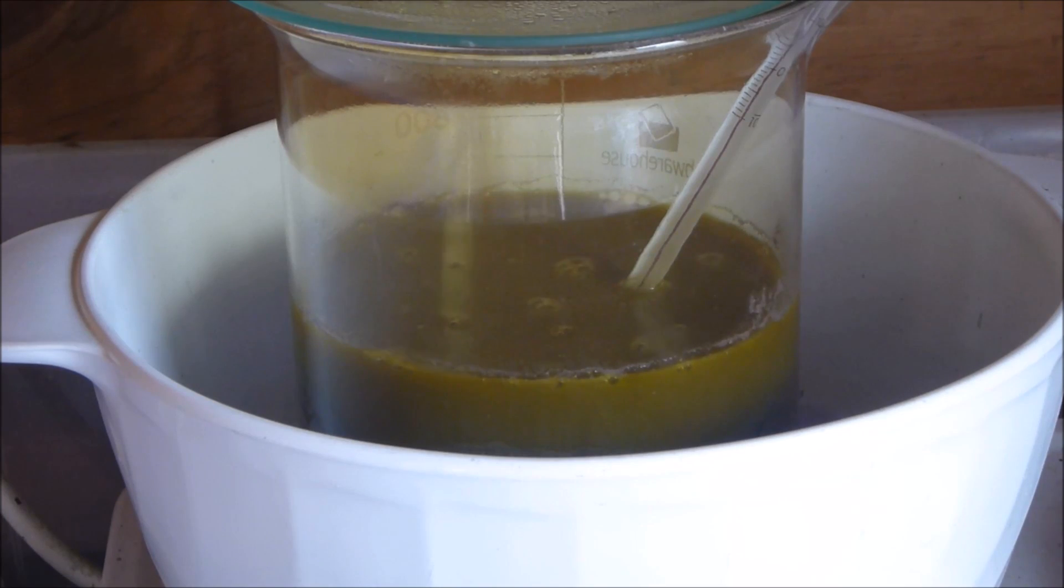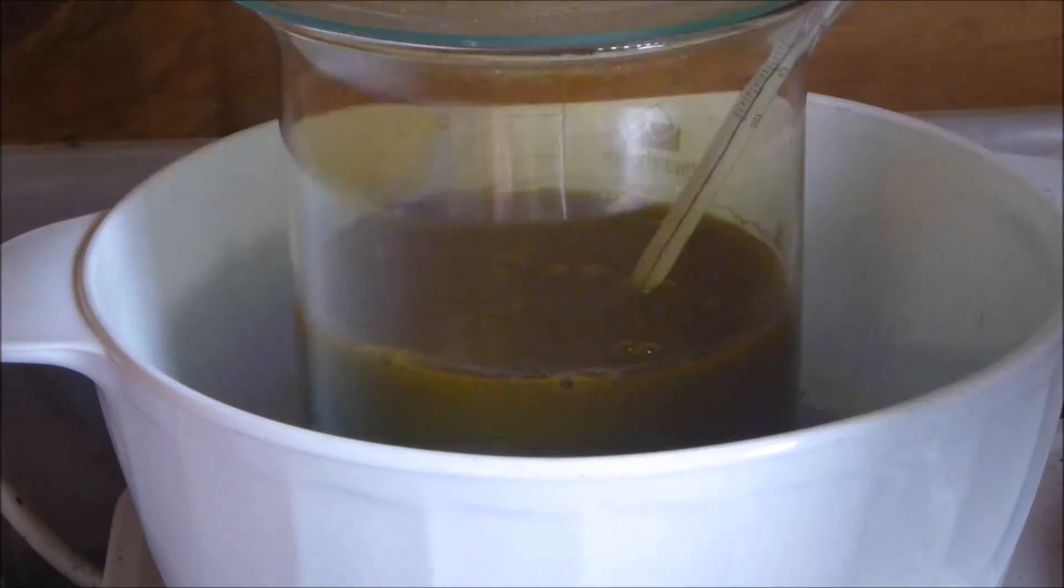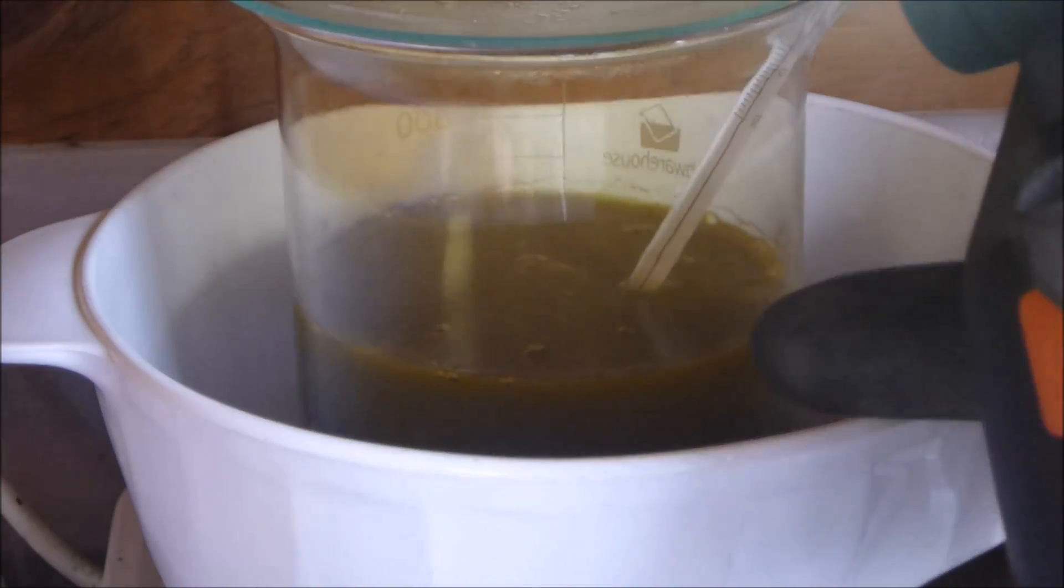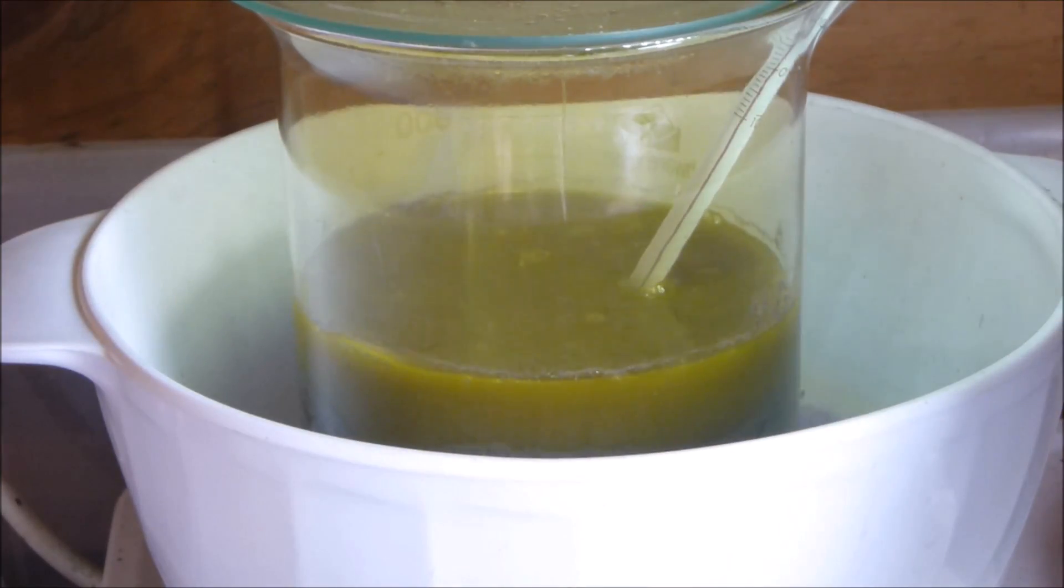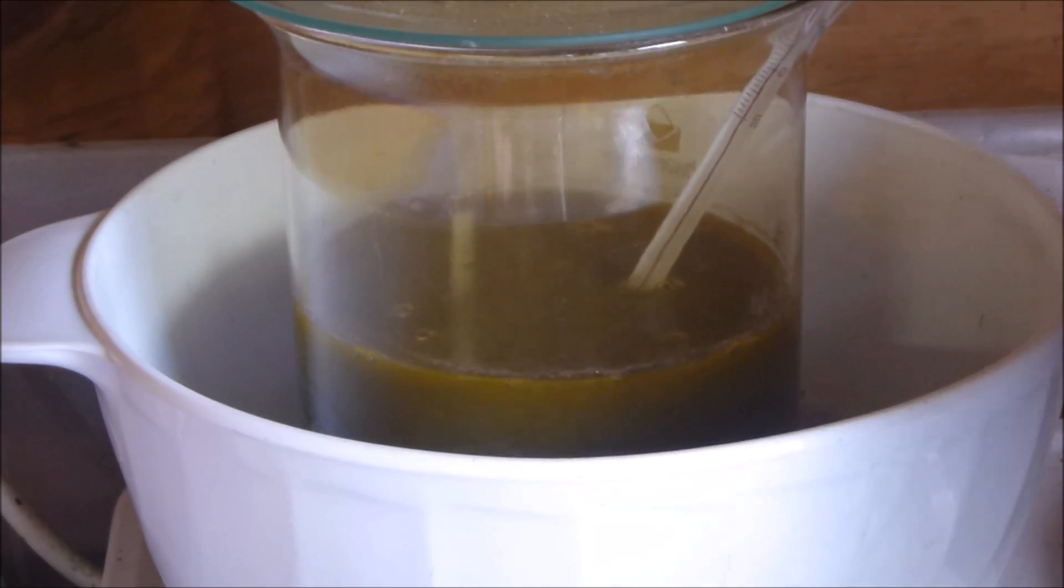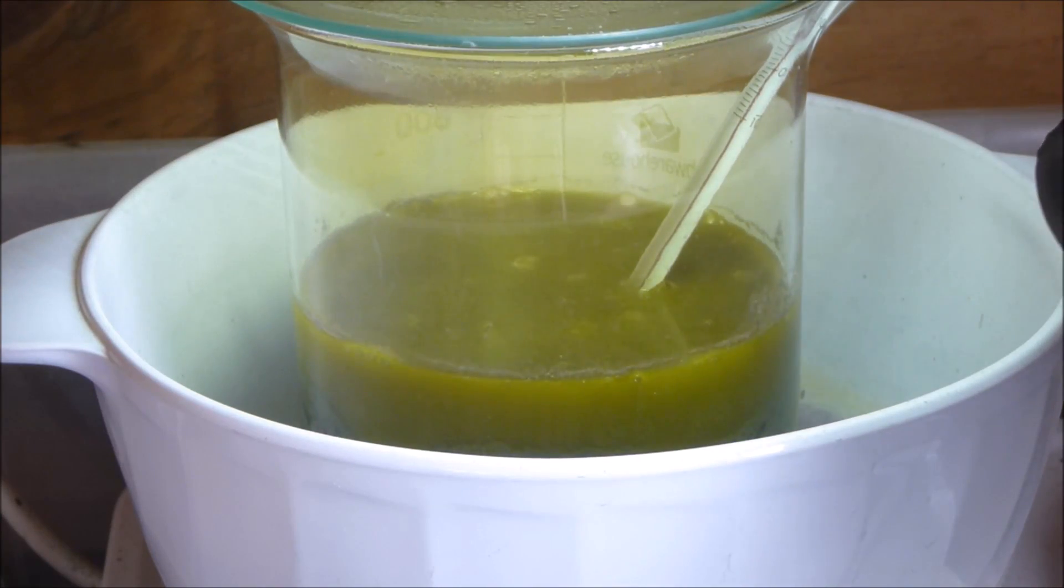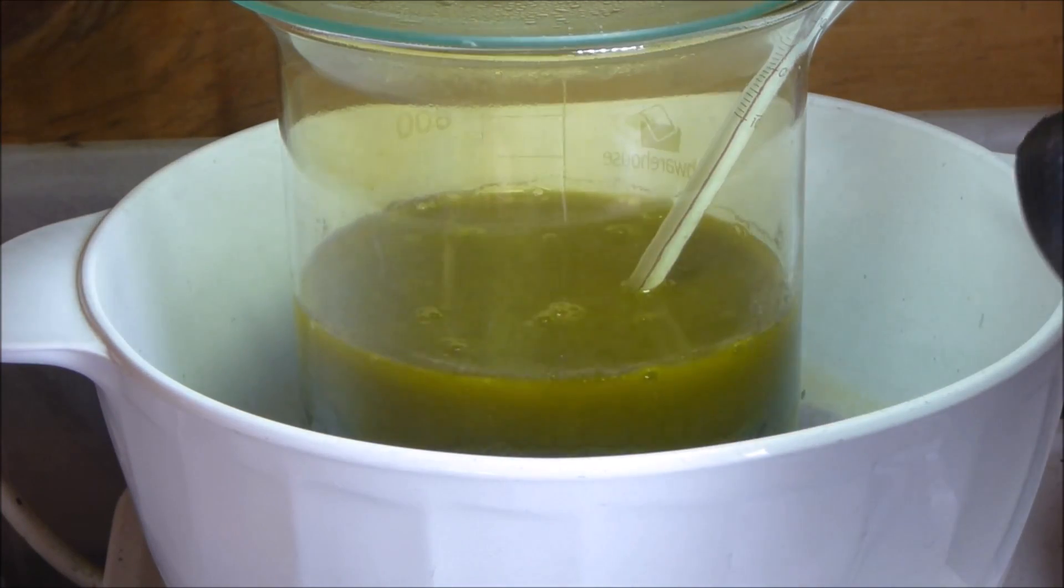Okay, so we have those ceramic ICs broken up inside here. I've covered it with hydrochloric acid and added about 100 milliliters of excess. I also added about 5 milliliters of nitric acid and then gave it a little bit of mix through.